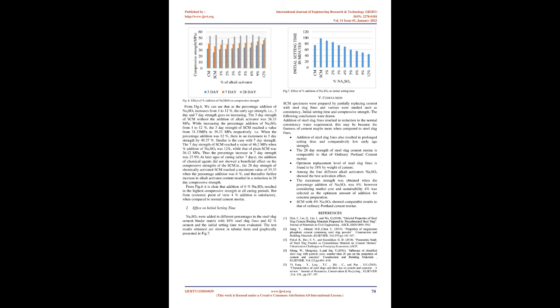1. On initial setting time of steel slag cement binder matrix. The initial setting time of cement paste with 18% steel slag fines after the addition of 6% of 4 different alkali activators is shown in Fig. 4. Fig. 4 Effect of activators on the setting time of steel slag cement paste. Initial setting time, minutes: OPC, Na2SO4, Na2SiO3, NaOH, Na2CO3.